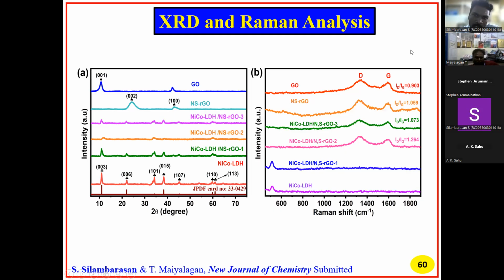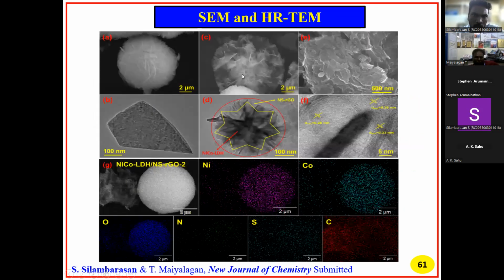Slightly the peak intensity shift is present. So, the SEM and HRTEM analysis: figure A is the pure nickel cobalt LDH for SEM analysis. Here the flower-like morphology, the nano flower-like morphology, is confirmed. Figure B is the TEM analysis of the layered double hydroxide, to confirm the pure nickel cobalt LDH.